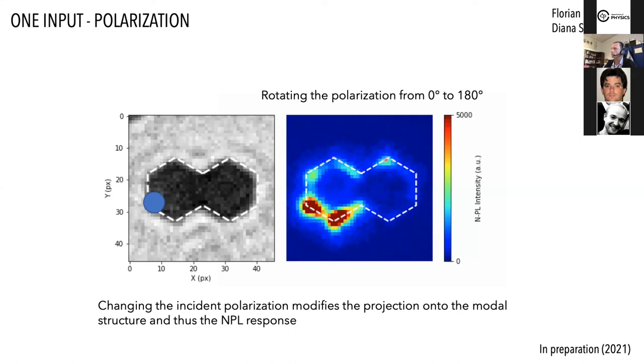You can see, for instance, here that this is lining up as a function of polarization. So basically, by changing the polarization, you project your signal onto different modal plasmon modes. And these modes are transporting the nonlinearity inside the structure and give rise to the signal. And this is how we're going to be measuring our logic gates.